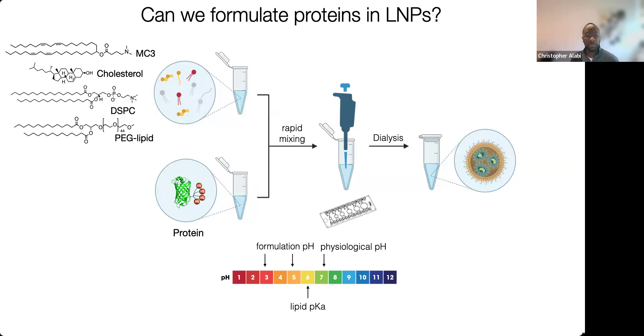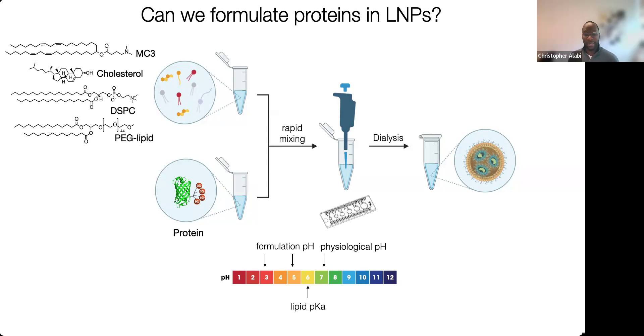These lipid nanoparticles work with a four-component lipid formulation: a PEG lipid for steric shielding, DSPC or DOPE for endosomal fusion and escape, cholesterol to stabilize the particle, and MC3 as the ionizable lipid responsible for complexing and endosomal escape. We typically formulate at a pH lower than the pKa of the ionizable lipid. MC3 has a pKa of roughly 6.5, so we drop the pH to 4 or 3 to protonate it. We must ensure the anionic feature is still anionic at this low pH — the primary reason for using sulfonates, since their pKa is well below 2. We then undergo rapid mixing — lipids in ethanol, proteins in aqueous — then rapid dialysis to give a lipid nanoparticle.